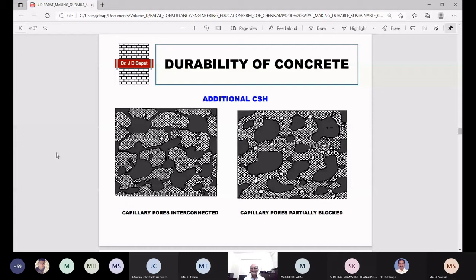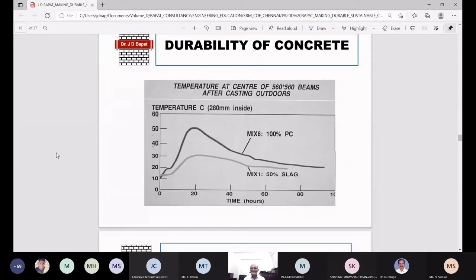Another effect of adding admixtures is that this is very beneficial for mass concreting. You can see in the plot that the temperature rise is drastically reduced when I add 50% slag in my concrete. You can see over there that the peak temperature has come down from 50 degrees centigrade to just around 30 degrees centigrade. So there is a huge reduction in the temperature of concrete, which is very beneficial for mass concreting. Like for example, you do a lot of mass concreting in dams. So there the temperature is very important.